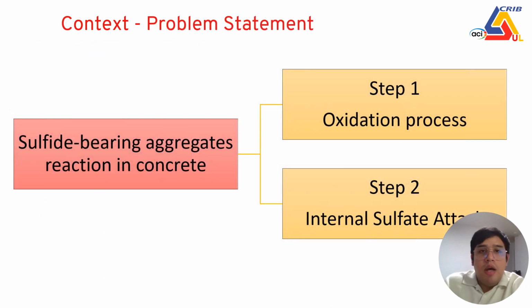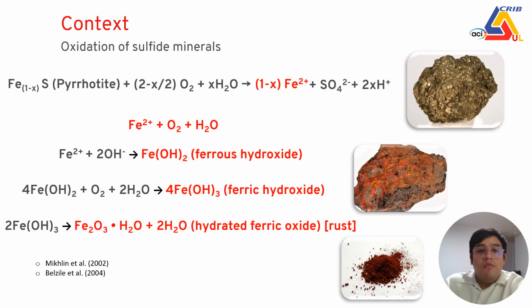So when we use this type of aggregates in concrete, two main reactions will happen if water and oxygen are available in the system. First is the oxidation process, and the second is the internal sulfate attack. I will explain in detail in the next slides. So for the oxidation process, we have the iron sulfide minerals, principally pyrrhotite, which is the most reactive one, that can be activated by the oxygen and the water, so the iron will be released and will continue reacting with the oxygen and water available in the system to form the iron oxides or the iron hydroxides, as you can see here below. And we know the most common is the rust material, but this is not the only reaction.